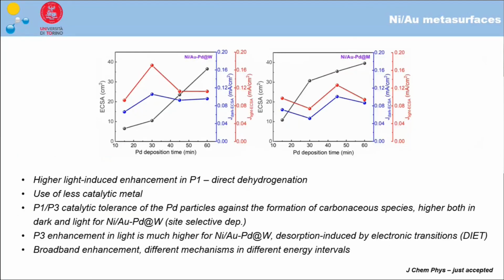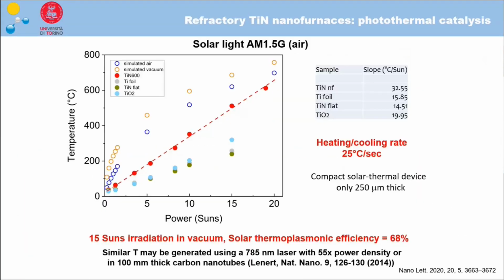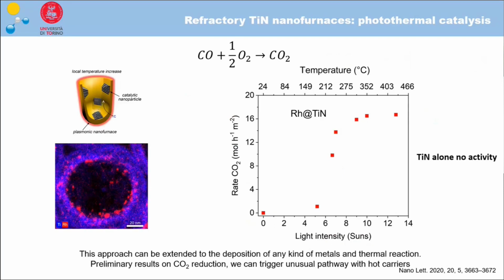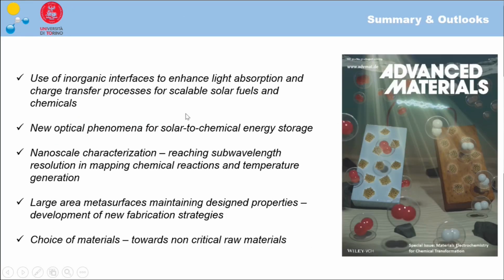So I will just show here the possibility to do also solar thermal catalysis using these materials, so we can achieve, for example, 600 degrees centigrade and use this for CO2 reduction or CO oxidation instead of using thermal reaction.